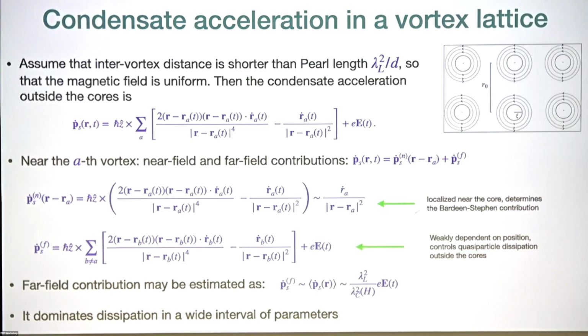Okay, so then to see what's going on, let's consider a single plaquette given vortex A, and I will isolate from this sum a contribution of this native vortex A. So this is what we call near field acceleration. It is inversely proportional to the square of the distance from the given vortex. But then the other vortices and also the uniform field create a far field contribution, which does not decay with the distance from the vortex core, is essentially uniform. And we can estimate this far field contribution to be just the average condensate acceleration in the sample. And it's given by the electric field times the ratio of these London to Campbell lengths.